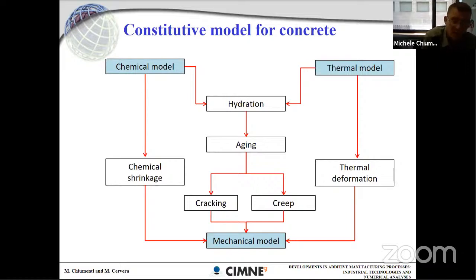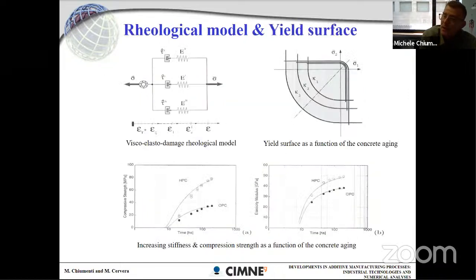So you want to go through hydration, aging, and you can have problem of cracking and creep. So not only thermal deformation, but also the effect of the water content. At the end of the day, the model that we typically used at that time was a viscoelastic damage model. Most of the work is done on the viscoelastic behavior of the material. Typically, we're using chain of dampers and stiffener, and you typically have an aging yield surface.